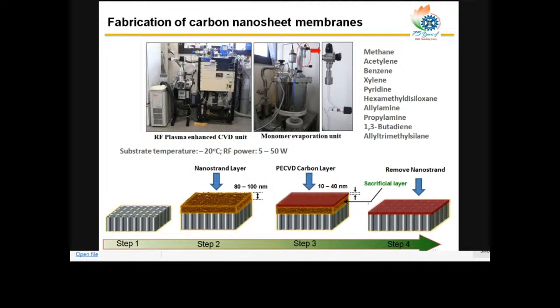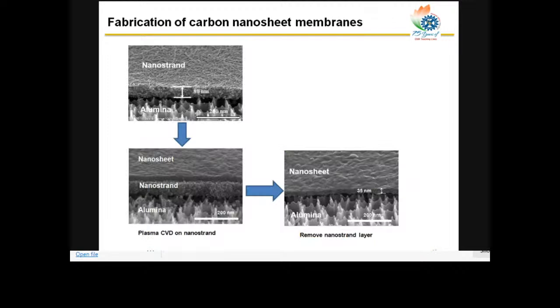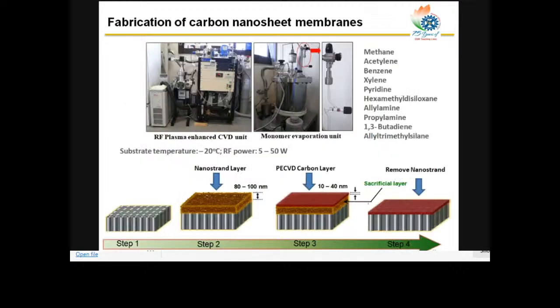plasma enhanced chemical vapor deposition to make a thin carbon layer. And finally, if we remove the nanostrand layer, we can have a freestanding nanosheet layer directly on top of the support. So what we have done, we took a support which has a bigger pore. We made a nanostrand layer to reduce the pore size. And then on top of the nanostrand, we made a carbon layer. And finally, after the carbon layer deposition, we removed the nanostrand layer to get a freestanding film directly deposited on the alumina support. This can be done with plasma enhanced carbon chemical vapor deposition.